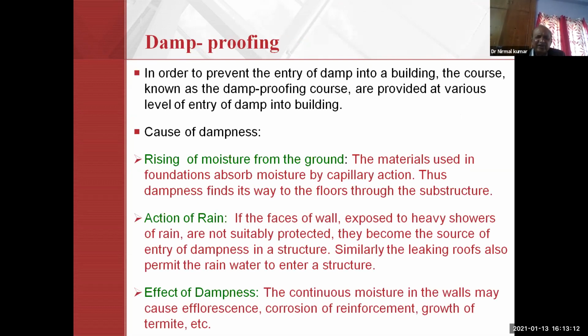Now the important aspect to maintain the quality is the dampness. Generally, you see there is a capillary rise of the groundwater into the wall, and therefore we should prevent this capillary rise of the water from the ground and the action of rains on the exposed surface of the wall, as all these are the possible causes of dampness in the house. Rainwater enters and capillary rise is also possible, and this will continuously moisten the wall of the house, which will cause efflorescence, corrosion of reinforcement, and growth of termite, and therefore it should be avoided.